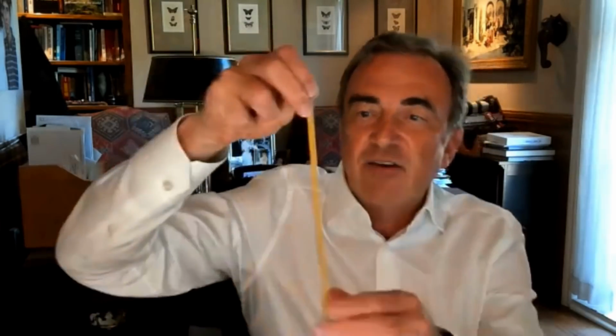As a matter of fact, the crazy part about our Sinanode process that people are completely baffled by is, they take a commercial graphite that has a surface area of, for example, 4 square meters per gram. They give it to us. We put it through our process and we give it back to them. And we say there is now 21% silicon nanowires on all the graphite particles. 21%. So if you start with, let's say, 100 kilograms, you now have 121 kilograms, okay? And then we say, please measure the BET surface area. And they know they started with a graphite that had 4 square meters per gram. And they know we added all of those nanowires that have nano dimensions.